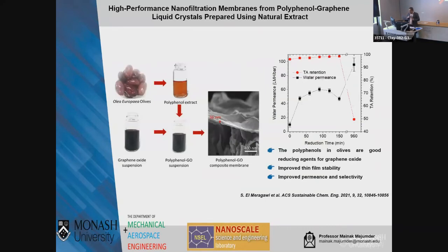The other paper which I'm showing here is a membrane. Membrane is a kind of flagship project in my group. What we did was we started to play around with the chemistry of polyphenols reacting with graphene oxide, yet maintaining the stability in a dispersion form, and then able to cast stable membranes of about 50 nanometer thickness. If you make thin membranes out of graphene oxide, it will be very unstable. It will dissolve in water. This type of material is stable in water. You can run for as many hours as you like.